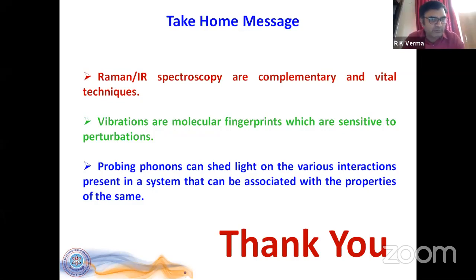Kapil Nayak has sent a question: how do the in-plane vibration and out-of-plane vibration change with the sample thickness, and what is the reason behind their change? I guess he refers to graphene. In both the cases, in-plane and out-of-plane vibrations, the moment we have more than one layer, the layers interact with each other through van der Waals interaction. That van der Waals interaction comes into play and makes changes in the vibrations of the phonons that we otherwise talk about in just a single layer. These interactions will change as we have more and more layers, and that is why both the in-plane and out-of-plane vibrations will respond the moment we have more than one layer.